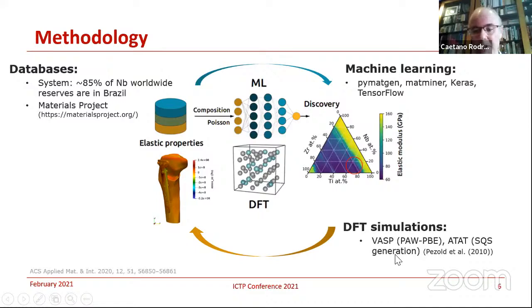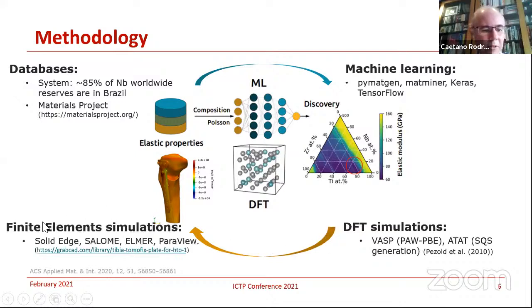Here, particularly, you have a problem that you have to use the special quasirandom structures in order to approach the alloy problems. Now, this information that comes from the density functional theory is then used to feed the elastic properties, where you perform some finite element simulations. You could see if the alloys and systems that you search are in good shape to be used in real conditions and also for real applications.